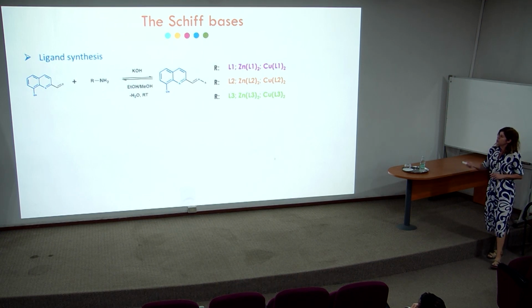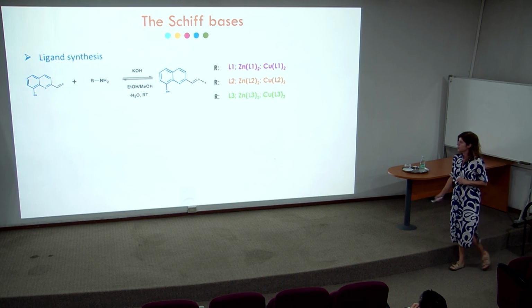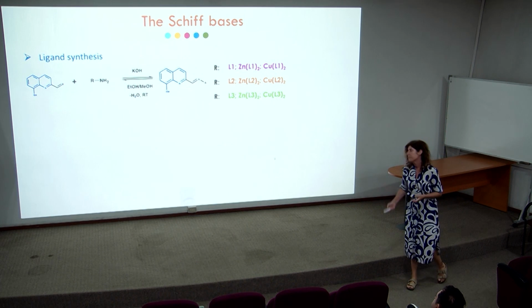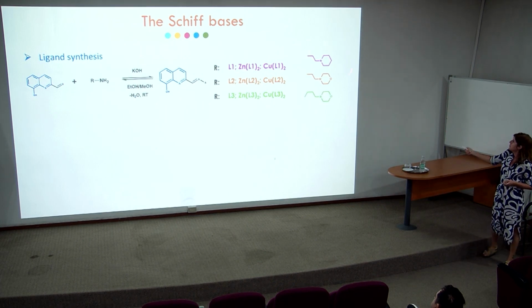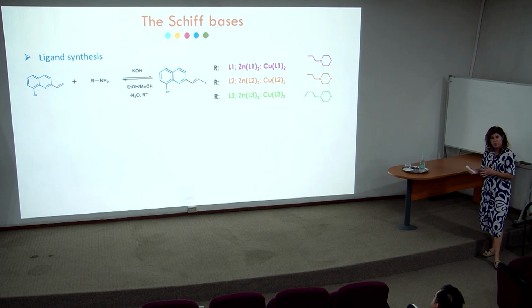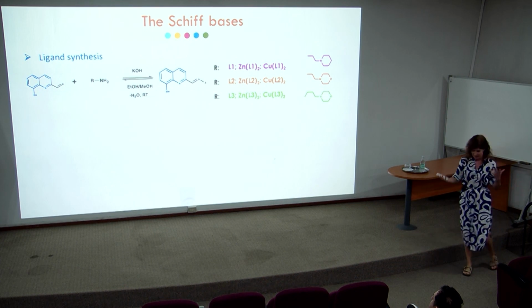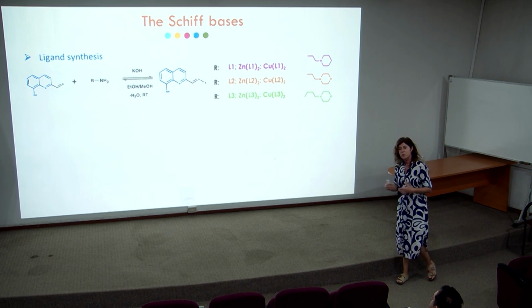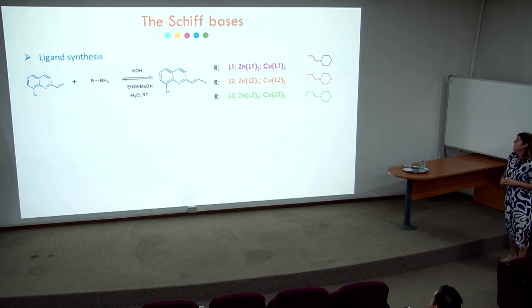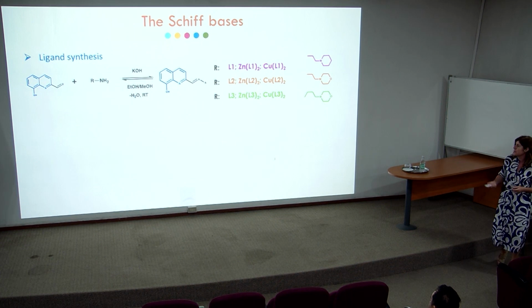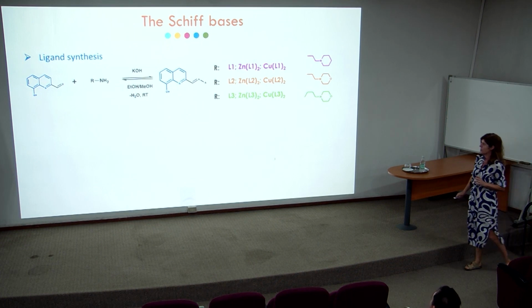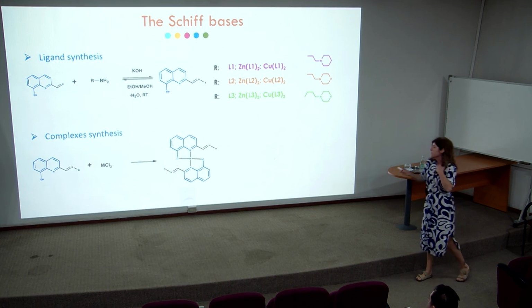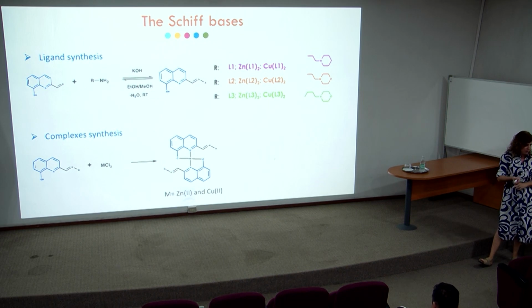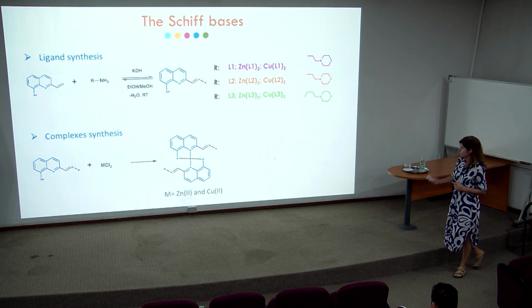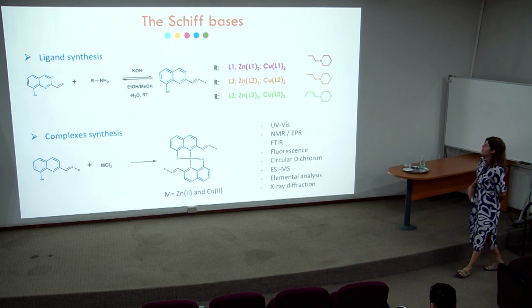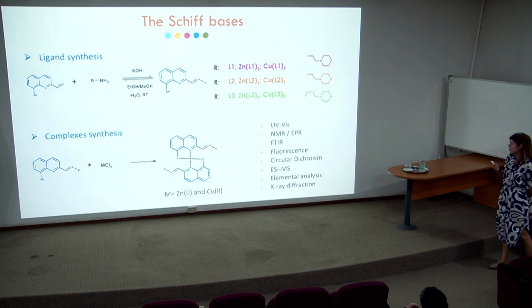So in this case, we also used the same aldehyde, the 8-hydroxyquinoline aldehyde, but we reacted it with amines. And as amines, we chose amines that have morpholine or piperidine moieties. Why? Because when these units are present in a ligand, we can get compounds with good cytotoxic activity. So joining these two units might be a good strategy. For the complex synthesis, we decided to use zinc and copper, and we obtained 1:2 metal to ligand ratio compounds. Of course, all the compounds were characterized by the usual techniques. I will show you just a few of them.